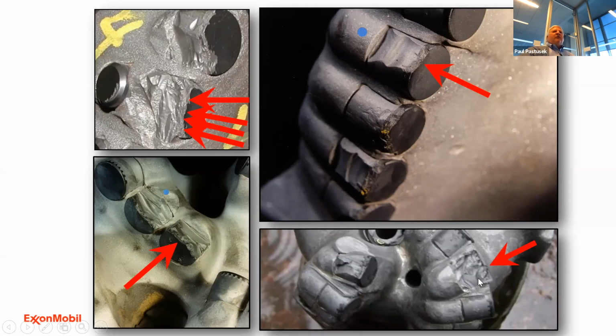So remember that first bit we showed you that was the 1-1? Here's that cutter on the nose that we told you about. I told you it was a broken cutter on the nose. The nice thing is now I know that this was tangential overload. Now, when it's tangential overload on the nose, that's very likely from drilling into a hard formation and taking too big of a depth of cut. So I structurally overloaded that cutter.